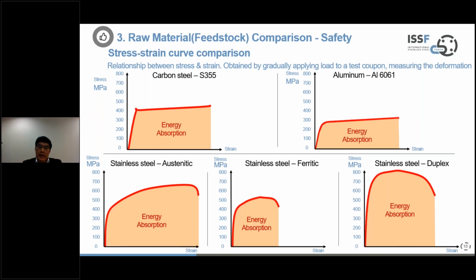You can see that each chart has a curve, and that curve states the yield stress. And you can also see that each chart has an area in pink, which means the energy absorption that's possible for these materials until the point of fracture. Now, if you compare the charts on the top and the bottom, you can see that for the most part, stainless steel holds a larger energy absorption area as compared to carbon steel and aluminum.